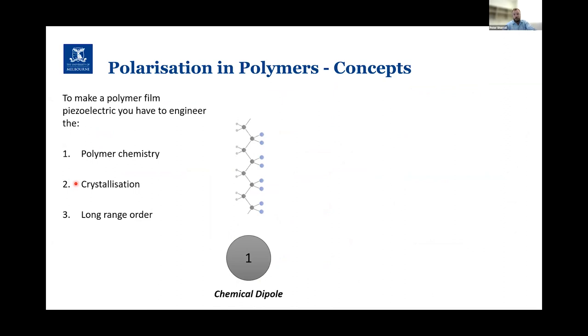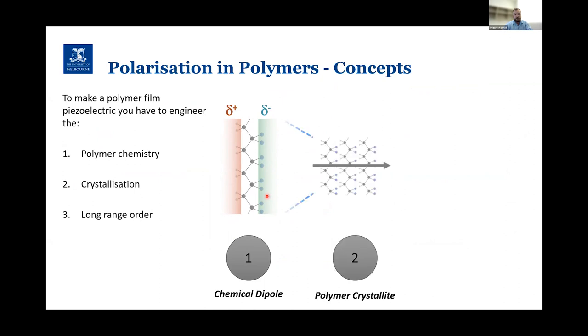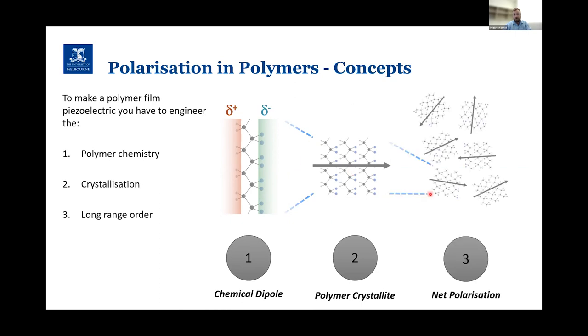What you need for something to take mechanical energy and make electricity out is a dipole moment across your polymer. So this is PVDF. You have fluorine on one side, hydrogen on the other. Electrons sit on the fluorine atoms because it's more electronegative, so you have a net dipole. That doesn't matter on a single polymer chain unless you align the polymer chains into some sort of crystallite. And it doesn't matter if you have an aligned crystallite, if all the crystallites don't align themselves within your polymer film, because they'll all cancel out, you'll get net zero charge.